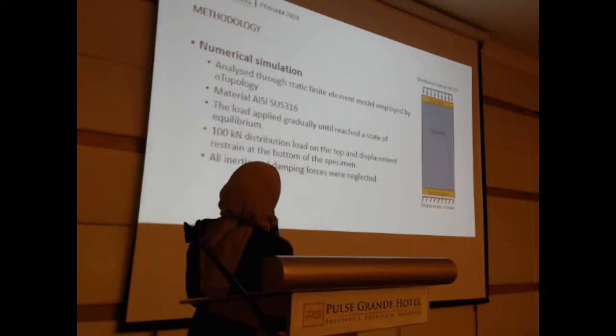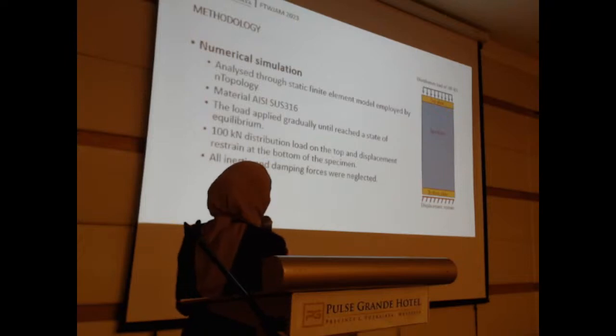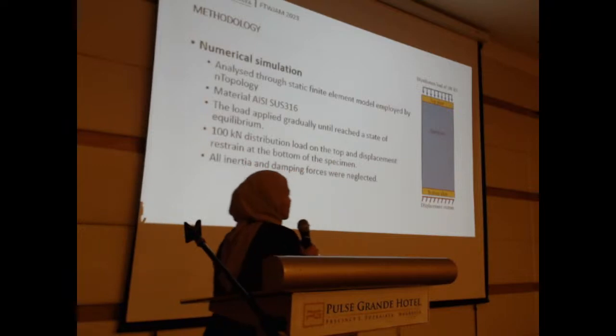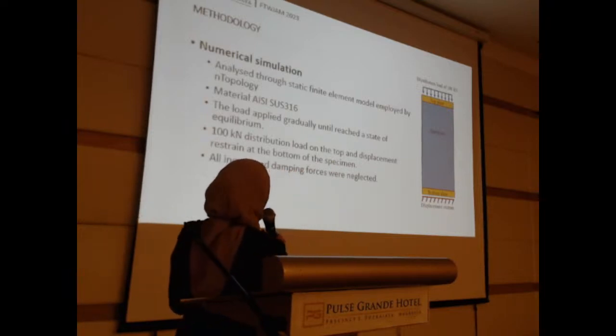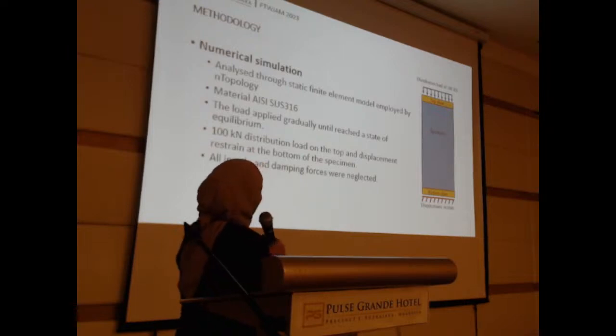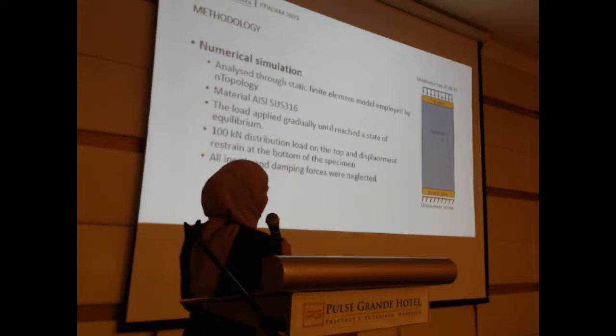Okay, numerical simulation was analyzed through static finite element, which is employed by nTopology. The material that was chosen is stainless steel 316. The load is applied gradually until it reaches a state of equilibrium, and the distributed load being used is 100 kilonewton on the top, and the displacement is retained at the bottom of the specimen, and all inertia and damping forces were neglected during this simulation.